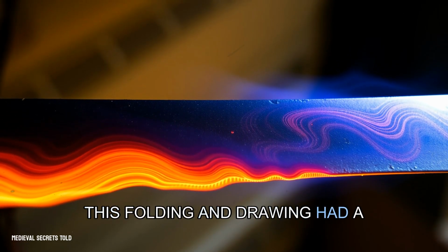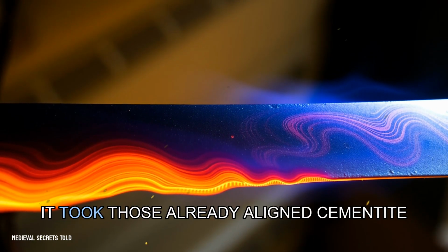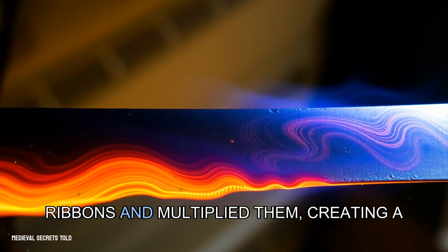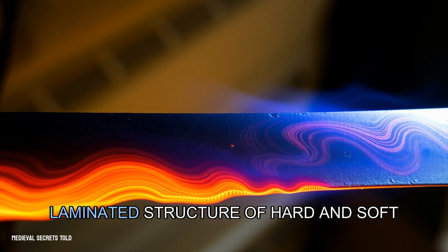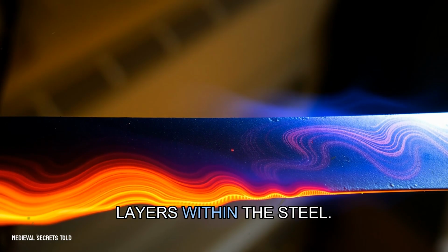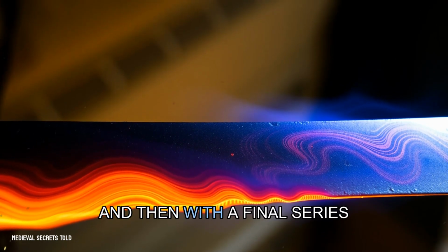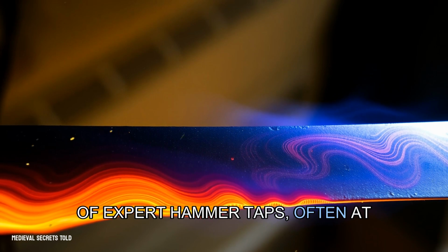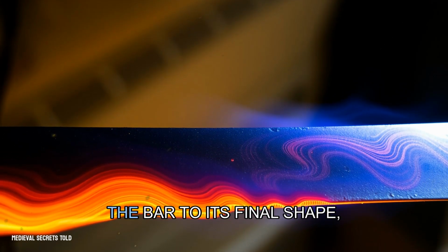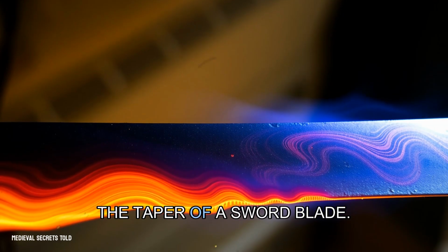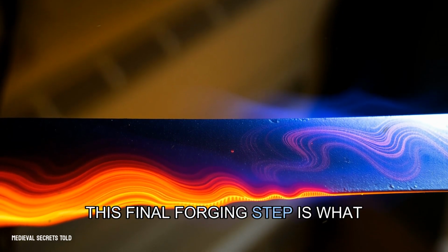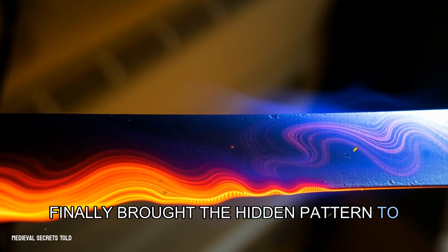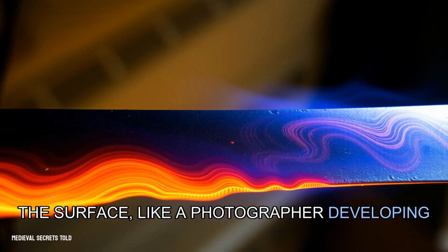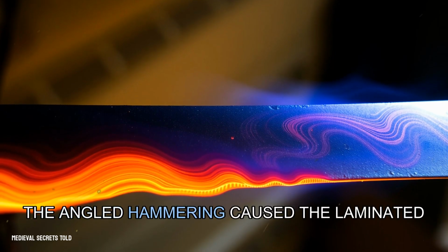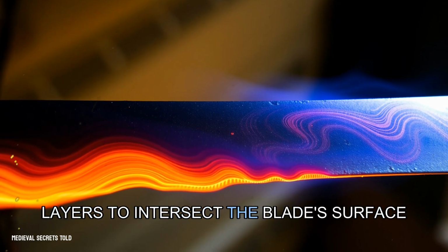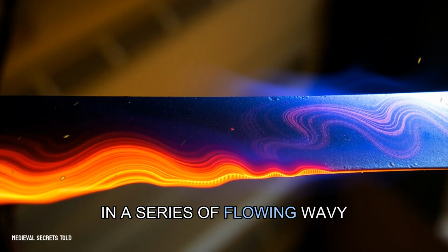This folding and drawing had a magnificent effect. It took those already aligned cementite ribbons and multiplied them, creating a laminated structure of hard and soft layers within the steel. And then, with a final series of expert hammer taps, often at a precise angle, he would draw the bar to its final shape, the taper of a sword blade. This final forging step is what finally brought the hidden pattern to the surface, like a photographer developing a latent image. The angled hammering caused the laminated layers to intersect the blade's surface in a series of flowing, wavy lines.